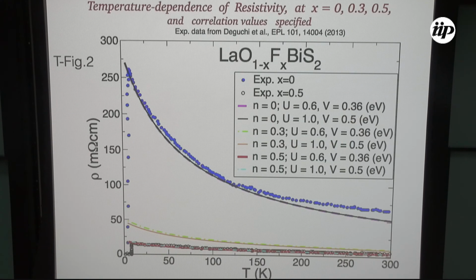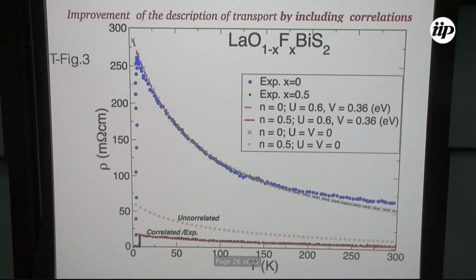So this is a result we obtained, for example, for the in-plane resistivity. Here the points are the experimental data for two dopings. You have 0, the parent compound, which is semiconductor-like, and 0.5, which has the optimal TC. We also put in an intermediate 0.3 doping. As you see, the description of the experimental points for this compound is really very good, even with two small correlation values. This one is smaller because it has to do with the other experiment and calculation I was telling you about, Eremin. But you see, it's almost equally good describing it with this U of 0.6 or 1.0. Here you see that they fit very well, and here it's also reasonable. Actually, it's better when you have some doping.